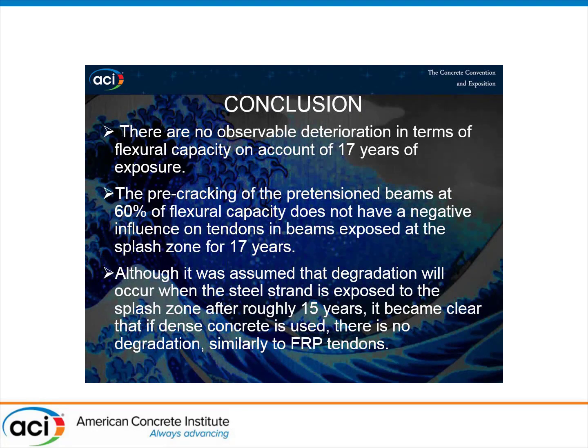And conclusion. In an effort to better understand the durability of FRP bar in a severe environment, a long-term study had been undertaken using tendons made of aramid and carbon fibers and steel strand in pretensioned concrete beams. As a result, it was confirmed that there is no observable deterioration in terms of the flexural capacity on account of the 17 years of exposure. The pre-cracking of the pretensioned beams at 60% of flexural capacity does not have a negative influence on tendons exposed at the splash zone for 17 years.